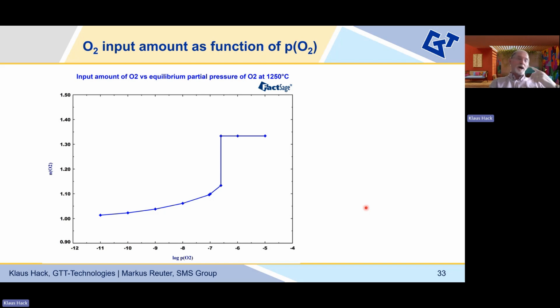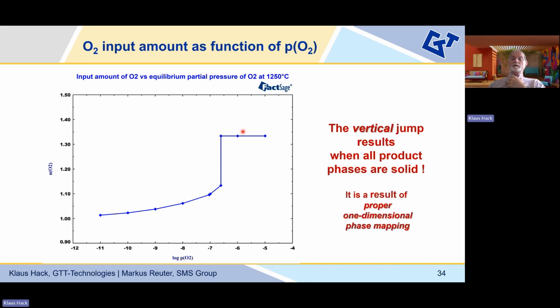then you can go backwards, and from each of these calculations where the oxygen partial pressure was fixed, you get an oxygen amount which is necessary at room temperature in order to reach this particular oxygen partial pressure at the high temperature. So here we now actually know how much oxygen we have to put into the system for the given range of oxygen partial pressures. That is now the result of a proper one-dimensional phase mapping through the system.